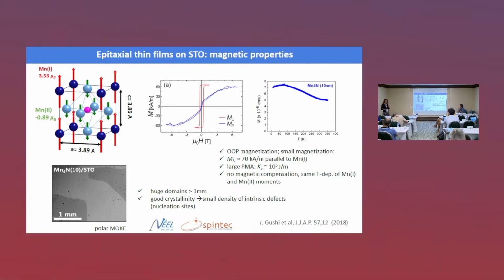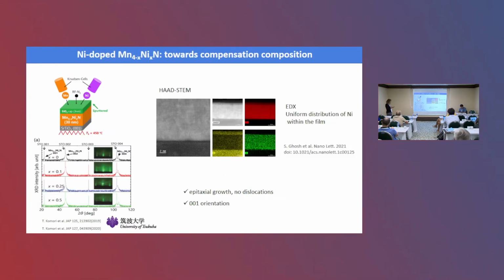We were surprised the first time that we put these thin films in our Kerr microscope, and we saw these huge domains, around 1 millimeter in size, which reveal the good crystallinity, so the very small density of intrinsic defects. So as I say, it's a ferrimagnet, but with no compensation.